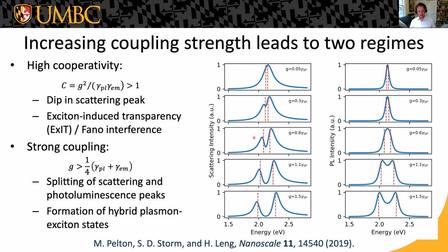But there's also an interesting regime in between, where I think most of you are familiar with this other figure of merit, which is the cooperativity. There's a different combination of the coupling strength compared to the cavity and emitter line widths. And in the plasmonic systems, you can get an induced transparency effect. You get 2 maxima in the scattering spectra, even when you only have 1 in the photoluminescence spectra, because of a destructive interference. It's sometimes described as a Fano kind of interference between the quantum dot and plasmon dipole, but I prefer to describe it as an exciton induced transparency that cancels out the dipole moment of the plasmon at the exciton transition frequency.